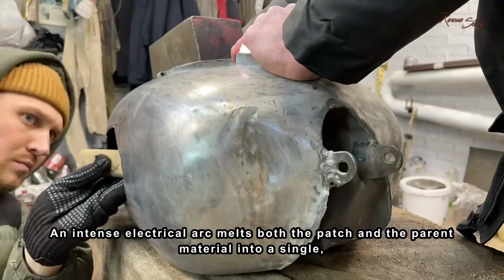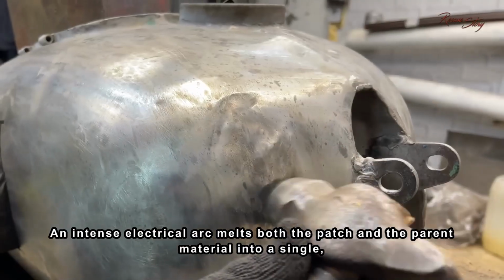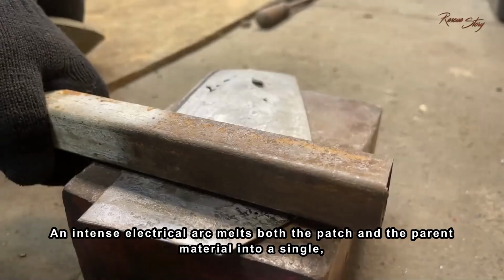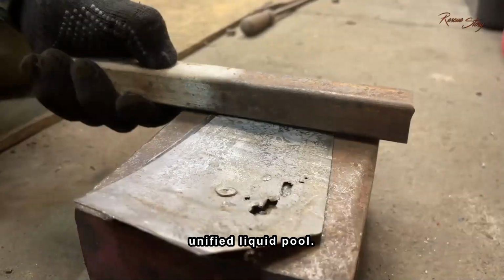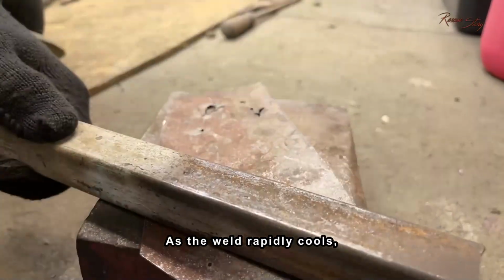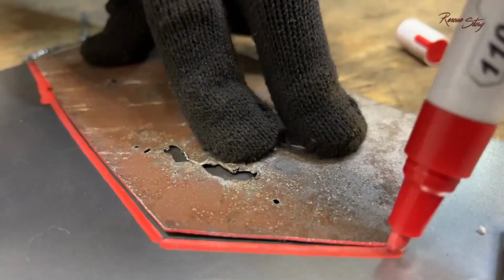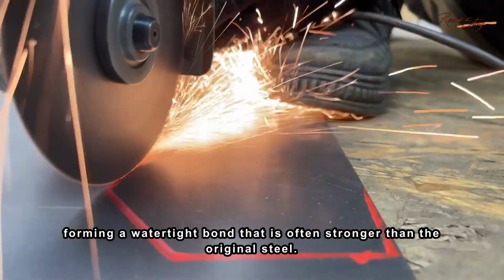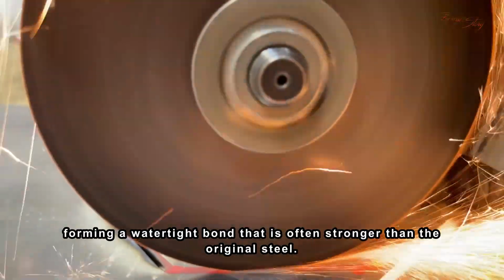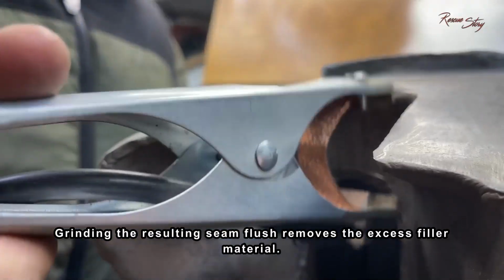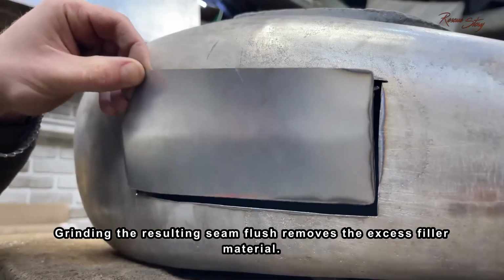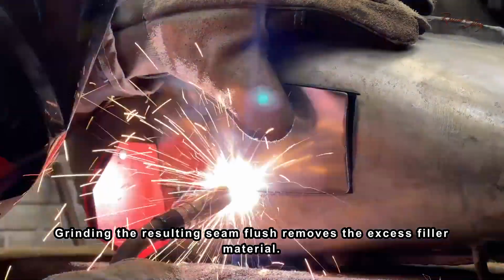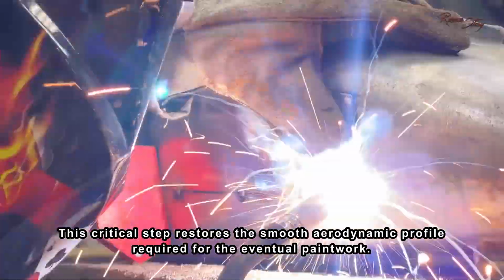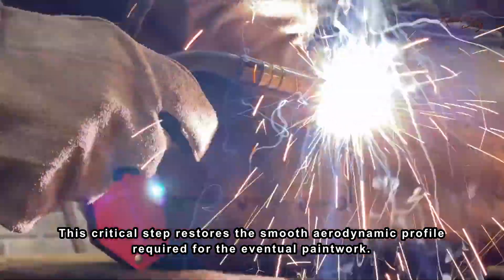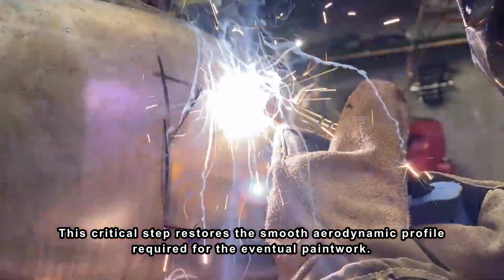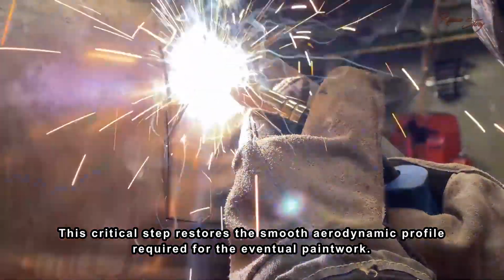An intense electrical arc melts both the patch and the parent material into a single, unified liquid pool. As the weld rapidly cools, it contracts, forming a watertight bond that is often stronger than the original steel. Grinding the resulting seam flush removes the excess filler material. This critical step restores the smooth aerodynamic profile required for the eventual paintwork.